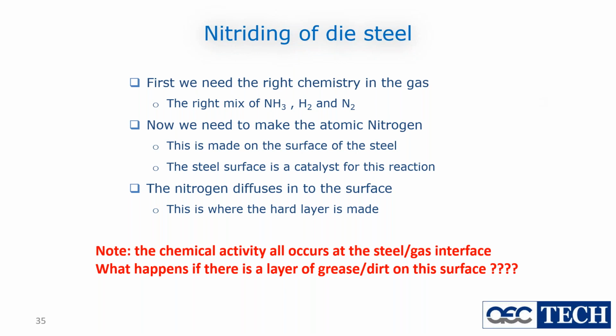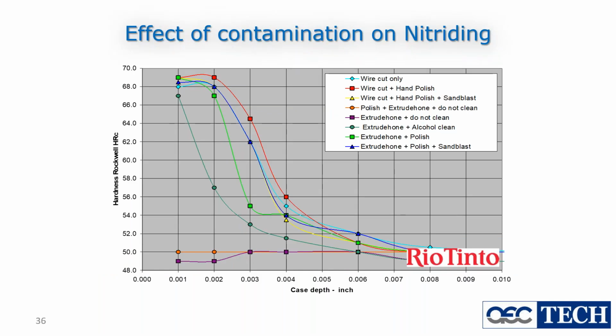This whole nitriding business is very key on the amount of steel that's in the reactor. If you put just one die into your nitriding reactor, it isn't going to work very well, because all the dissociation constants for breaking the ammonia up and making nitrogen are based upon the volume of steel inside the reactor. A lot of places I've worked in will keep a whole load of scrap dies, which they just use to fill up the reactor if they don't have a full charge that day. That way they keep the amount of steel in there. Those also have to be cleaned, by the way. So what happens if you've got some dirt on the surface?